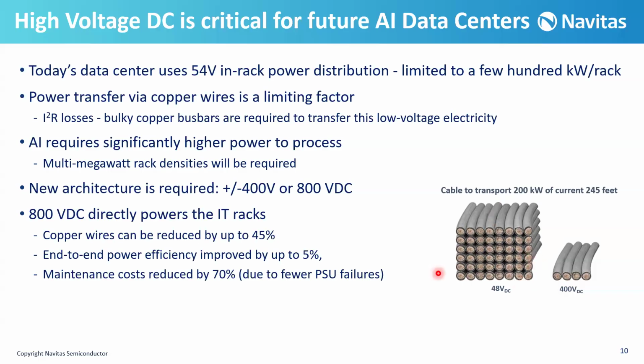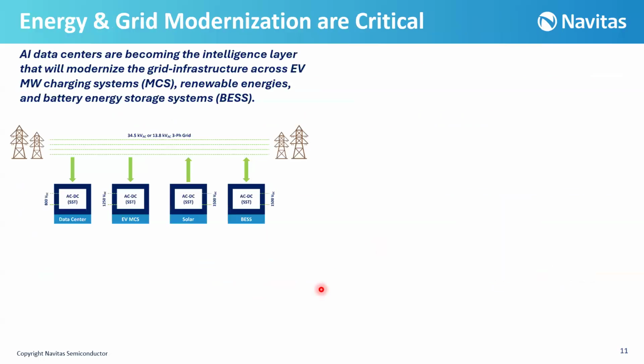And finally, 800 volt DC directly powers the IT racks. It means that the copper wires can be reduced by up to 45%, as I explained here. End-to-end power efficiency improved by up to 5%, and maintenance costs reduced by 70%. And the reason is we have fewer PSU failures.